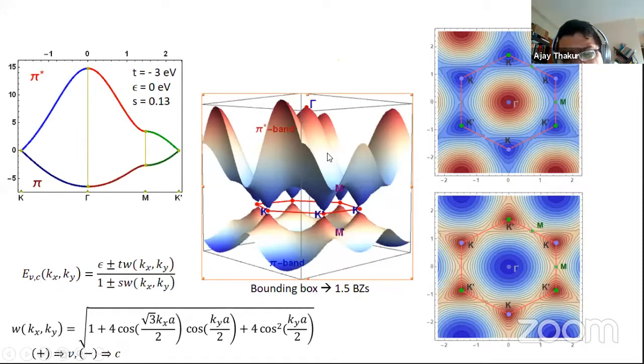If we look carefully, this top picture corresponds to the pi star band, where this red has the highest altitude and blue has the lowest altitude. On the other hand, here in the pi band, you can see that this blue has the lowest altitude, and this brown has the highest altitude again. But now these browns are at the K points. So this corresponds to the top of the valence band. And in this case, these points correspond to the bottom of the conduction band.